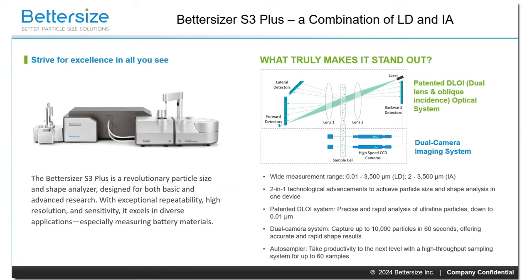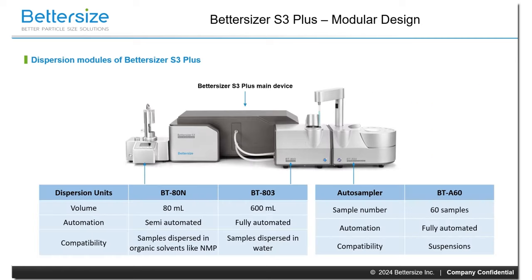For the laser diffraction part, the Bettersizer S3+ is equipped with a Bettersize patented dual lens and oblique incidence system, to ensure the accuracy of measurements, even for the finest particles down to 0.01 microns. For the image analysis part, the Bettersizer S3+ has a dual camera system to rapidly and accurately capture flowing particles.